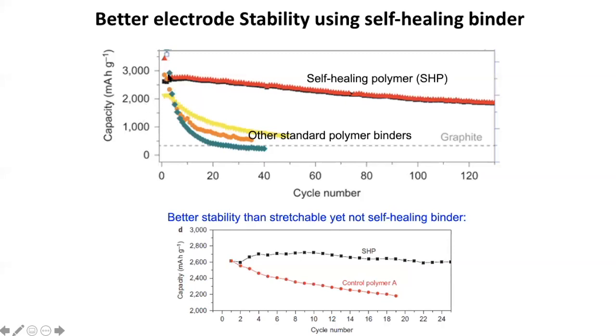We want the battery to maintain high capacity. So here, close to 3000 milliamp hour per gram, this is what silicon anode can get us. As a comparison, the dashed gray line is what graphite can do, and you can see graphite holds much lower capacity compared to silicon. And compared to these conventional polymers, using self-healing polymer we can maintain many cycles of charging, discharging, and still be able to operate the battery.